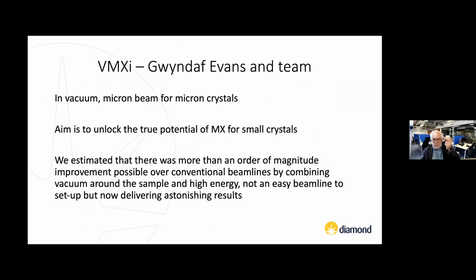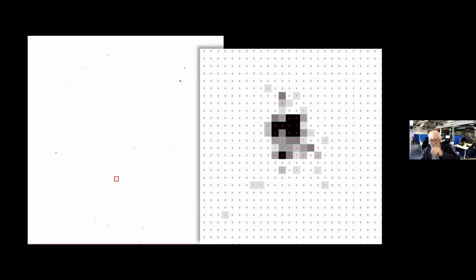Then the final thing is something that's just coming online, and this is a really challenging beamline led by Gwyndaf Evans, where he's trying to work with micron-sized crystals, micron-sized beams in vacuum with high energy X-rays to really revolutionize what you can do with microcrystals. And we thought that there was at least an order of magnitude improvement to be gained if one did this. And just now this is being demonstrated.